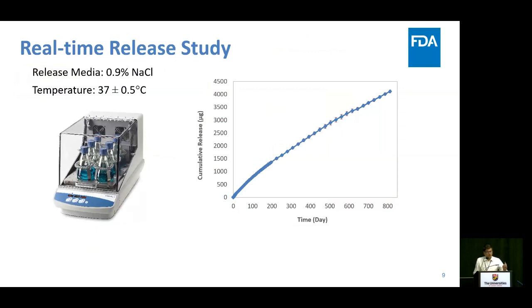What is important in this study is that if we look closely at the initial hours of this curve, we'll see a phase change from first order to zero order. The initial first order release indicates the release from the saturated membrane, and the transition from first order to zero order indicates the establishment of steady state. So this also supports our initial hypothesis that the drug release starts from a saturated membrane.